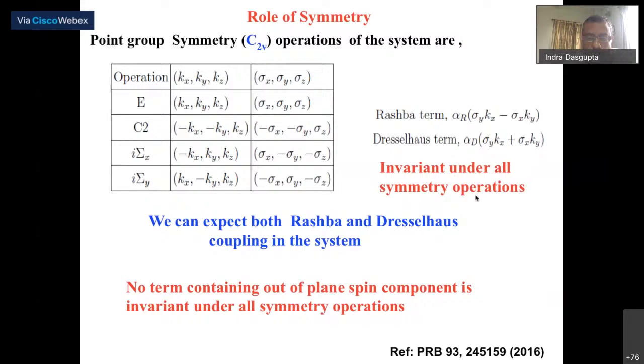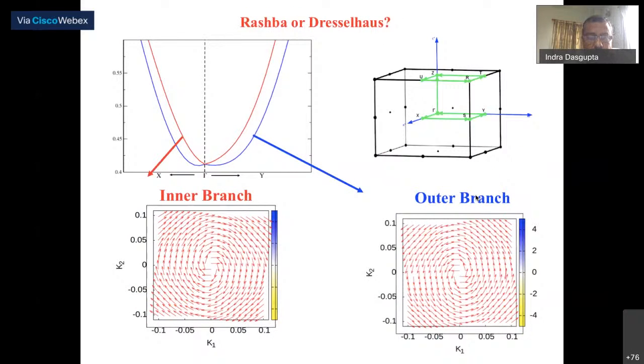And of course, we have to do model calculations. This is precisely what we have done. We have looked at the points around the gamma point, and we can clearly see that the band splits because of this spin orbit effect. Once we calculate the spin texture, we find the spin textures are chiral, characteristic of a Rashba effect. That's very good. This is from a full-fledged DFT calculation. We can do slightly better. And as I pointed out from symmetry, there's also a possibility of the Dresselhaus effect, but somehow it doesn't get manifested here. And the reason is why it doesn't get manifested here.